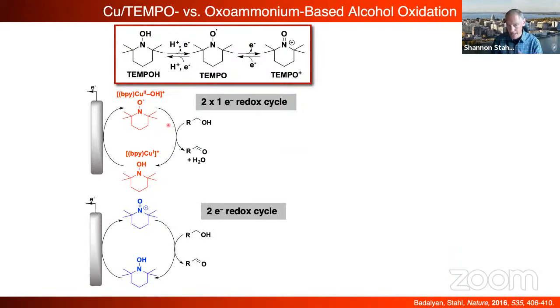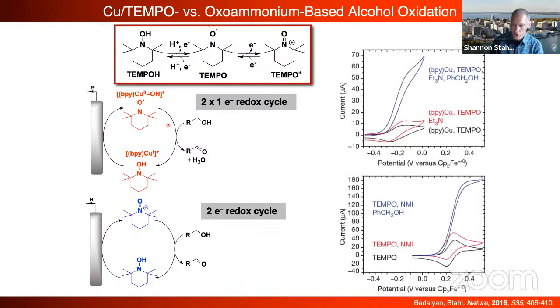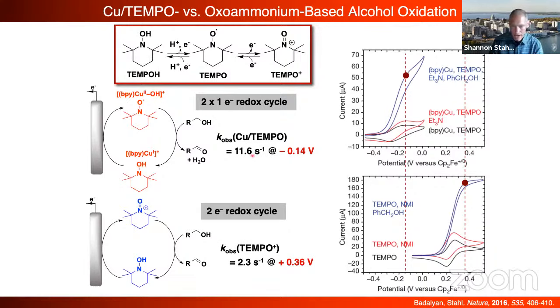Okay, so we hook those up to an electrode to assess their driving force for alcohol oxidation, anticipating that there should be a difference. Sure enough, there is a difference to the tune of about 0.5 volt. The copper TEMPO system is about 0.5 volt lower in potential relative to the nitroxyl. And if you actually use the electrocatalytic data and analyze the rates, what you find is copper TEMPO is like 5-fold faster than the oxoammonium. This says that a weaker oxidant is actually functioning faster, and that undoubtedly reflects the mechanism of the alcohol oxidation, which just creates lower barriers and still has adequate driving force to drive the alcohol oxidation. So even though it's a 0.5 volt weaker oxidant, it's still driving alcohol oxidation to the tune of 5-fold faster than your conventional oxoammonium pathway.